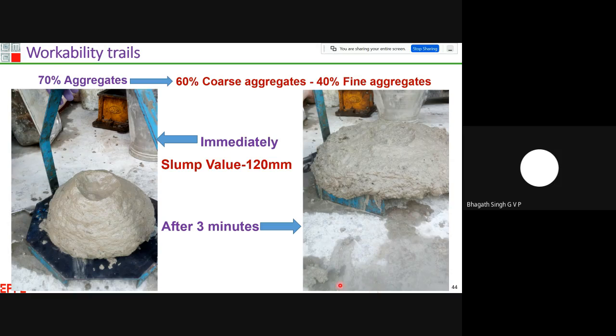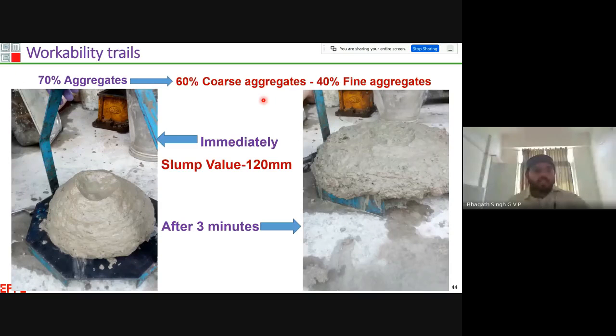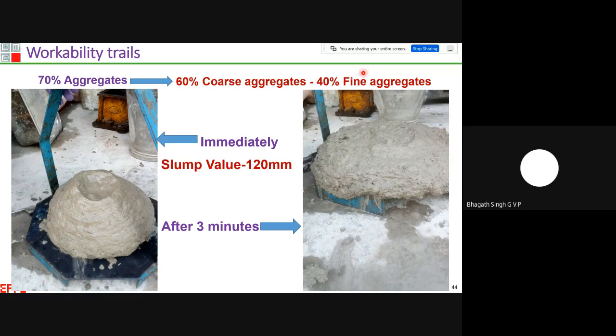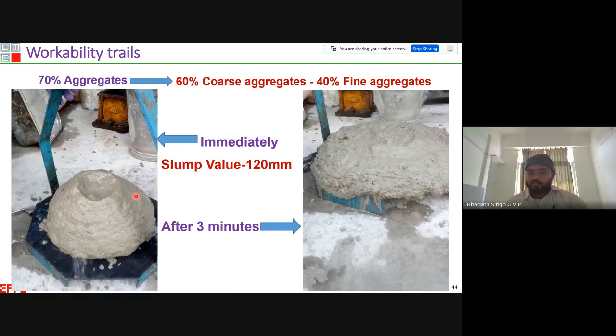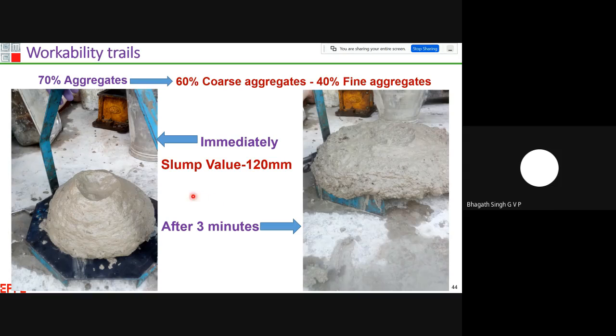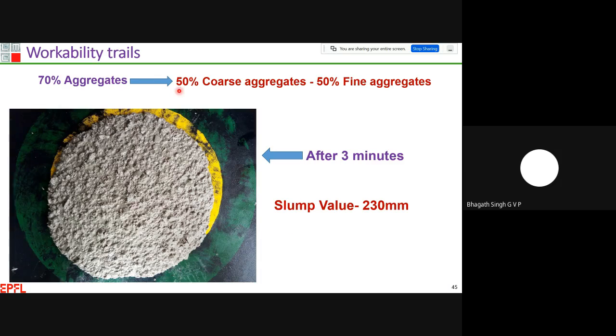These are weight fractions. Here we have conducted a few workability trials at our laboratory. At 70% aggregates, I have further divided it into 60% coarse and 40% fine aggregates. This is the slump I can see immediately once I have cast, and once we lift the slump cone, I can see 120 slump. After 3 minutes, you can see the slump has completely collapsed. Similarly, if we change the proportion to 50% coarse and 50% fine aggregates, after 3 minutes I can see the slump value is about 230.